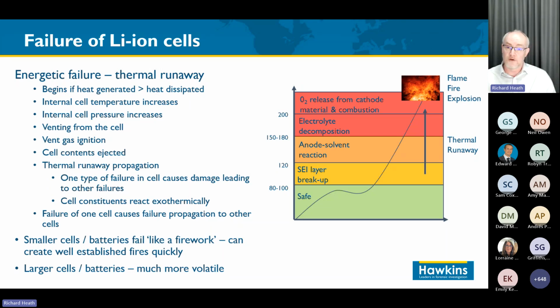And the problem is if one cell goes into thermal runaway in a battery pack, the heating of that cell can then cause the adjacent cells to begin heating and send them into thermal runaway. So you get this propagation of the failure mode from one failing cell through the other healthy cells in a battery pack to get a much larger failure. And I've always thought that the smaller cells, the individual cylindrical cells, you can think of them as being a little bit like a firework when they fail. And they vent the gas and they produce flames. It's a bit like setting off a firework in a room.